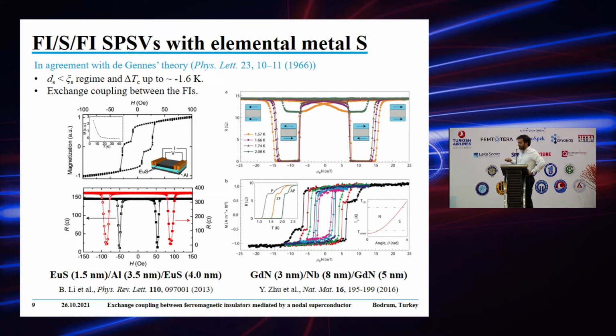In this case, what they observed was that when you go below Tc, there is an increase in the MH loops of the regions where the two ferromagnets are in an antiparallel state, which extends beyond the switching fields, so the coercive fields, of the two ferromagnetic layers. And they interpreted this as the superconducting condensate forcing the two gadolinium nitride layers to couple antiparallel, because that's the favorable situation for superconductivity. In a BCS superconductor you have these spin singlet Cooper pairs, so the energetically favorable state for the system is when the two ferromagnetic insulators are pointing antiparallel, because you reduce the pair breaking effect of the exchange field at the two interfaces.